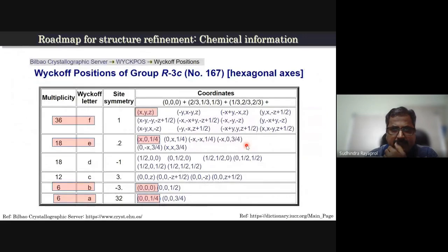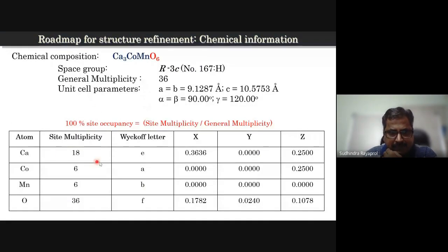Now, how the atoms are chosen is that you take one general position, you have to take the position in such a way that it actually satisfies your geometrical conditions also. So when you test these positions in refinement, your atomic positions and scattering, systematic absences have to be correct. Okay. So you have to place certain elements at these 4 sites. So how I have done this, that calcium I have put at 18.